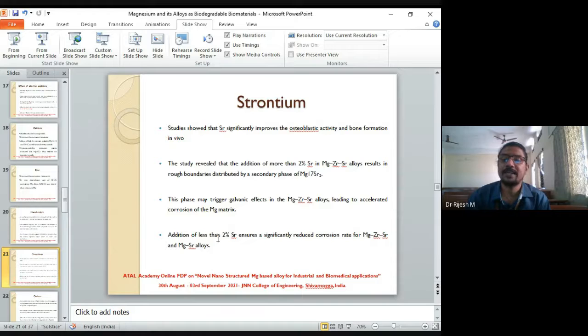So addition of less than 2% of strontium ensures significantly reduced corrosion rate. So whenever you are adding strontium, make sure that you are not adding more than 2%. If you're adding more than 2%, it will actually multiply the corrosion effect.